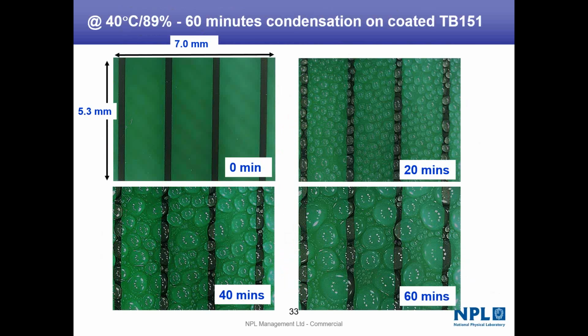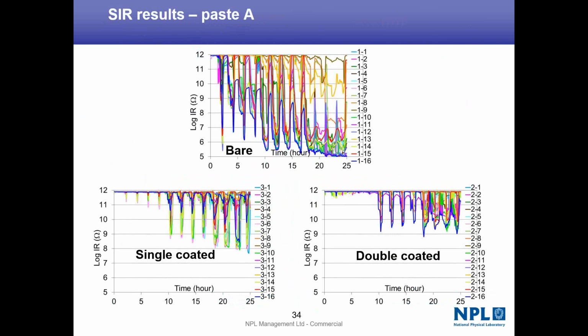Now this allows us to assess conformal coating materials, base materials, track and gap widths, cleanliness. So it allows us to do a number of things when we've got a standardized test method which consistently forms a condensation on the surface of the printed circuit board. Now what I've done here is just taken some results again from some of the tests. These were boards we built in Sweden with the assistance of a number of paste manufacturers.